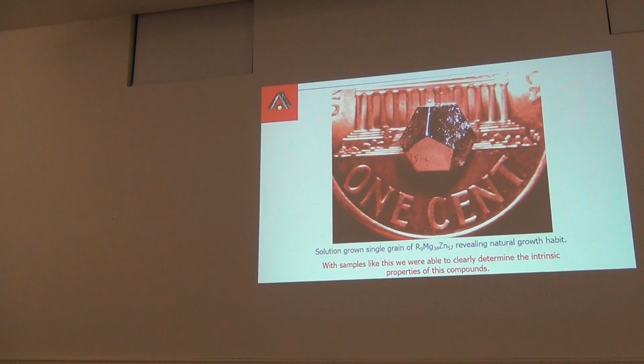This is, at the time, a remarkable single crystal because this was a macroscopic pentagonal dodecahedron. This clearly manifests the morphology of a forbidden crystallographic symmetry, 5-fold. This is what convinced a lot of people that quasicrystals actually were real. Okay? They should have believed the scattering data and the other things, but seeing something macroscopic helps convince you. Great. Now we have a pretty sample.